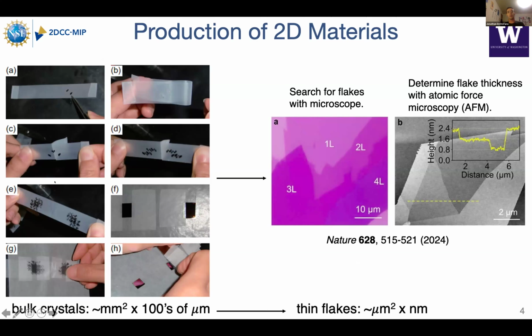And the idea is you can then put this onto silicon, and if you peel up this tape slowly, hopefully you'll get some thin flakes that are left behind on the silicon, which you can search for with an optical microscope, like shown here on the right. The different layers will have different colors. And you can verify what your eyes are seeing, as well as determine the actual thickness, by using an atomic force microscope, where you're dragging a cantilever along the silicon substrate. When you feel the presence of some flake, the cantilever will move, and then you can figure out the height that it moved, and thus the height of your flake.